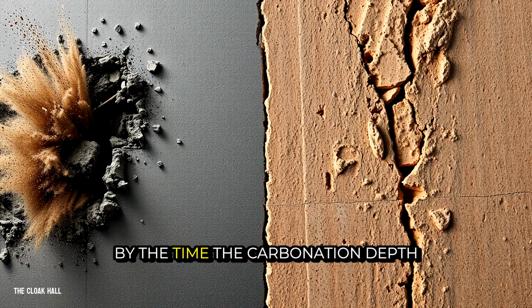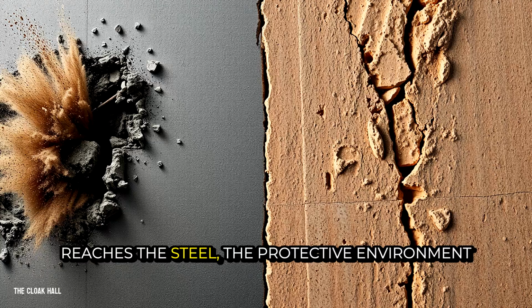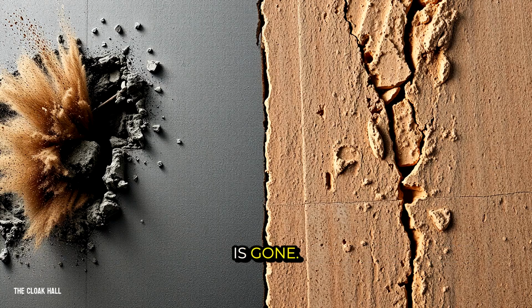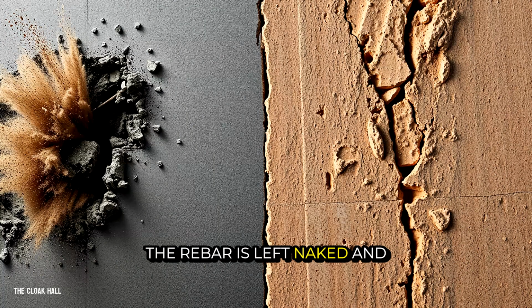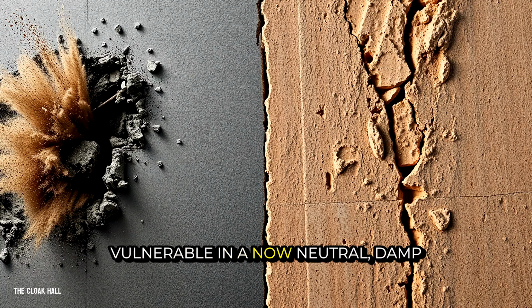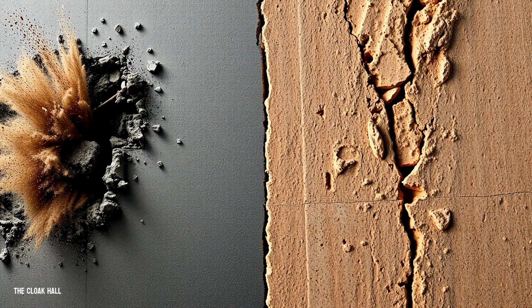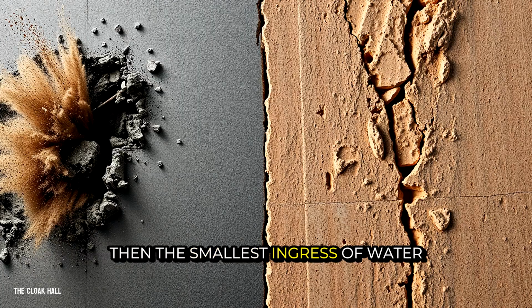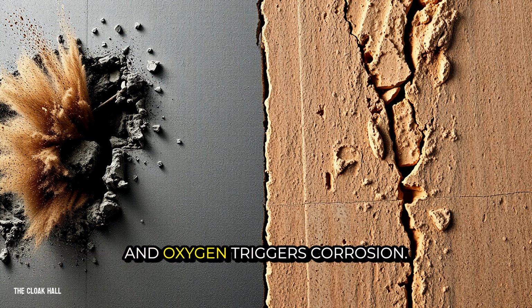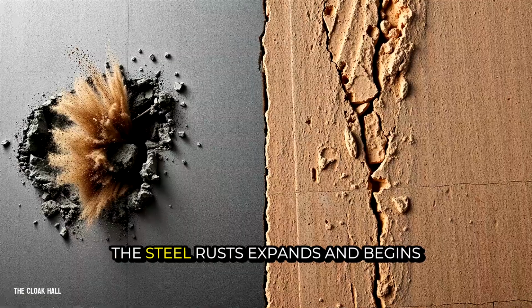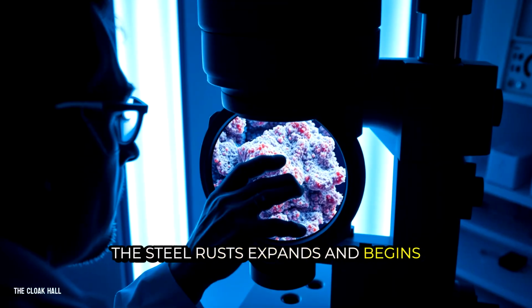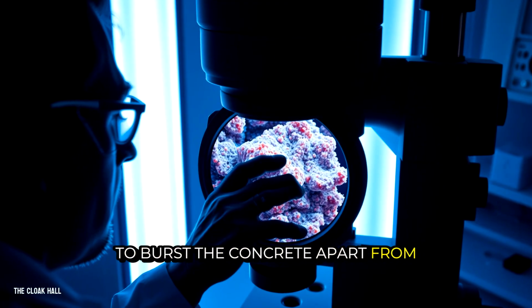By the time the carbonation depth reaches the steel, the protective environment is gone. The rebar is left naked and vulnerable in a now neutral, damp environment. Then the smallest ingress of water and oxygen triggers corrosion. The steel rusts, expands, and begins to burst the concrete apart from within.